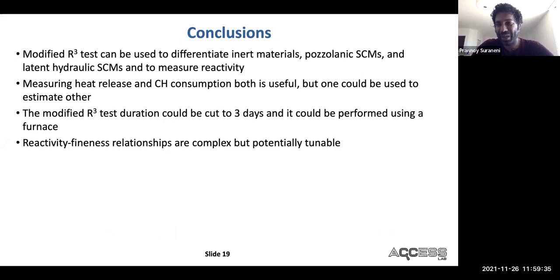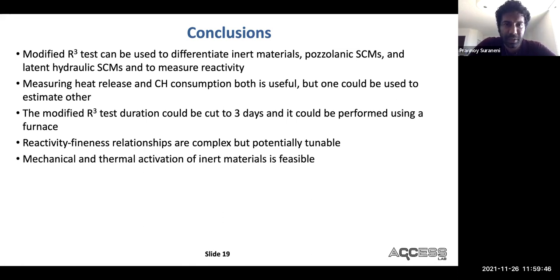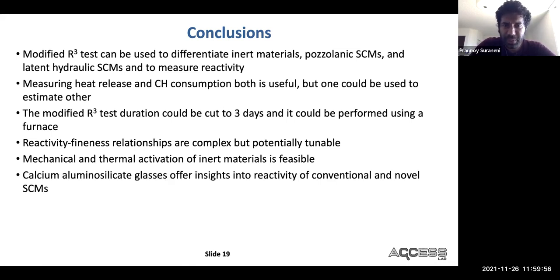Reactivity fineness relationships and how processing affects reactivity, it's incredibly complicated, but there is the possibility of tuning it using, for example, grinding aids, which is interesting. We've shown that mechanical and thermal activation of inert materials is feasible. However, there is some non-linearity. The mechanisms are still being explored. Calcium aluminosilicate glasses can be really nice model systems, and they can offer exciting insights into reactivity of both conventional and novel SCMs. And we're exploring their reactivity, the kinetics, and how it's affected by glass structure.